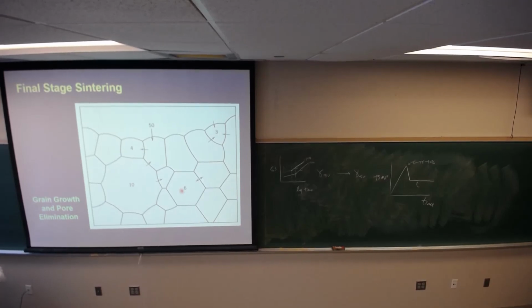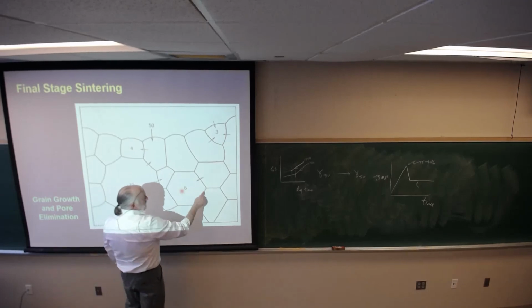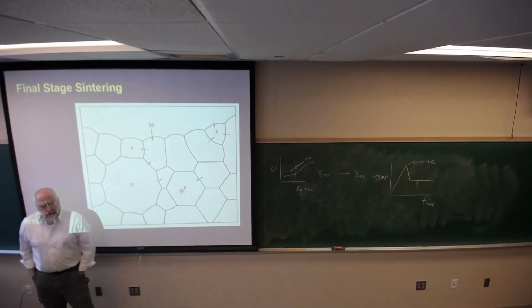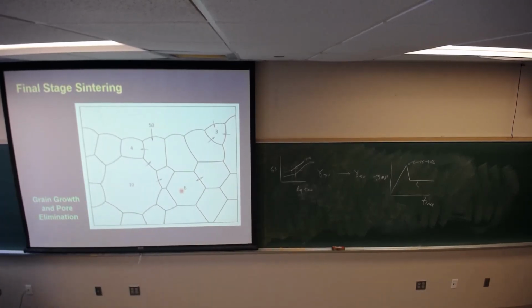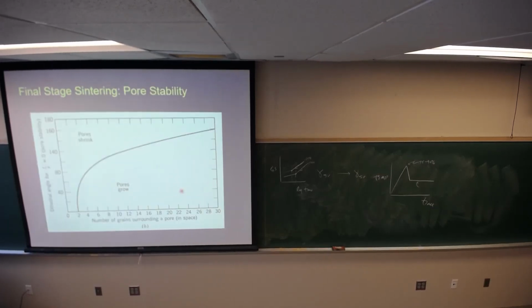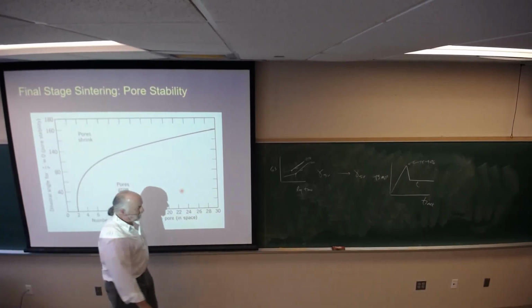Okay. Now this would argue that I have an equilibrium dihedral angle. That's this angle here, and it's 120 degrees. And if I have that equilibrium dihedral angle in an isotropic material, then the grains don't want to grow if they have 6 sides on them. If they have 7 sides, they want to grow. If they have 5 sides, they want to shrink. And there's a nice plot that predicts that. So what you have is dihedral angle. What's a dihedral angle? So this.